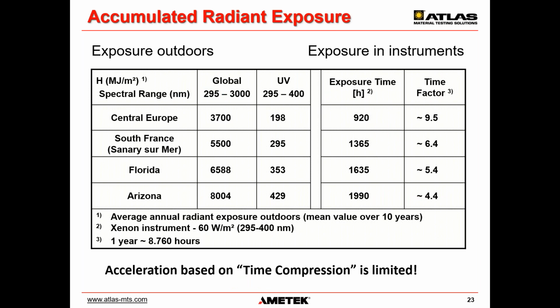So here's a list of average outdoor annual radiant exposure values just for your reference, and the associated exposure times in hours here in the instrument if it runs at 60 watts per square meter with no dark phase. And these are the time factors or acceleration factors you can calculate from that, with all due disclaimers and cautions, etc. So the maximum acceleration you can reach by compressing the radiation time is limited, below 10.